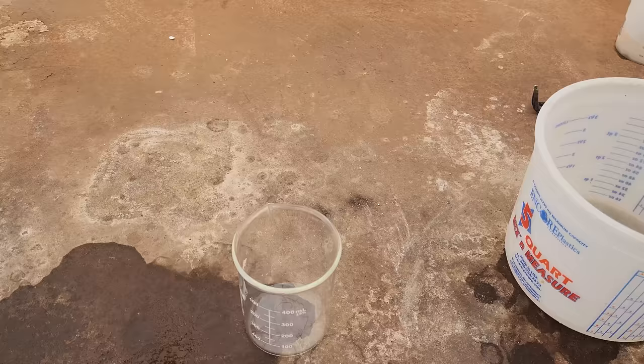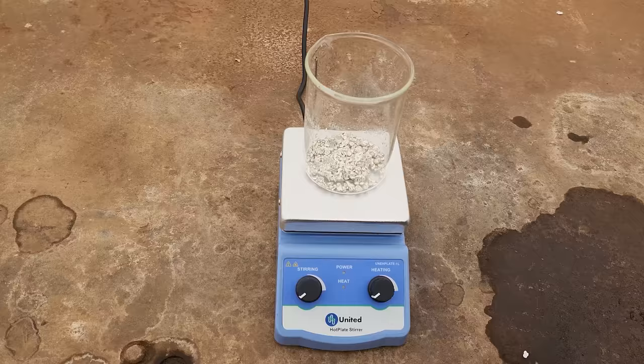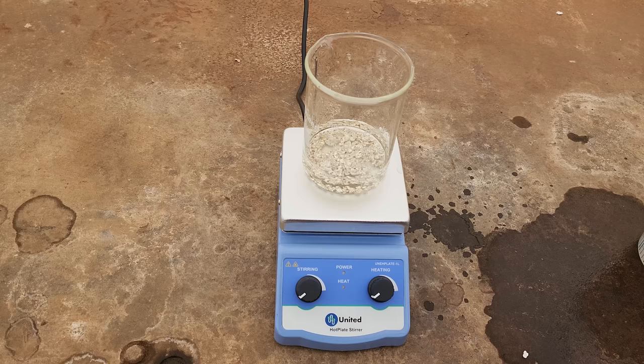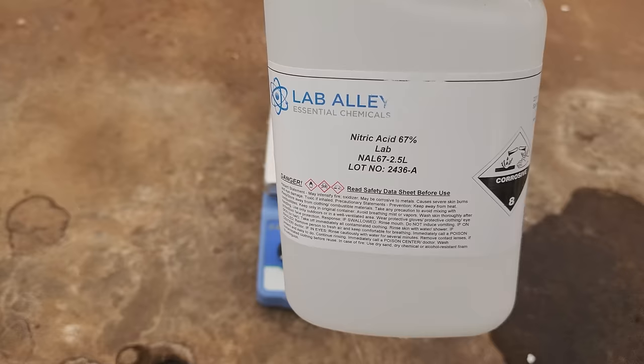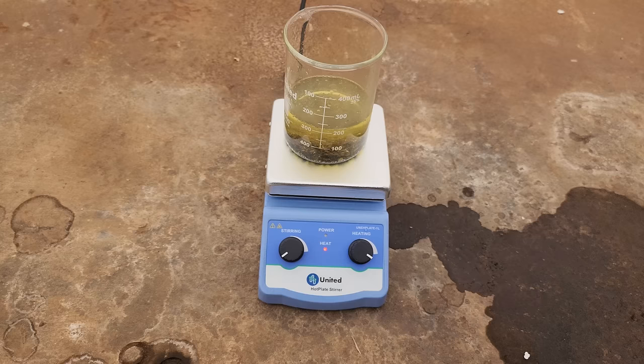Now I'm going to get all of our alloy moved over to this beaker here. I'm going to add about 100 milliliters of water. Then I'm going to add about 100 milliliters of nitric acid and turn the hot plate on and we'll get this boiling. But there's going to be some nasty fumes coming off of there, so I'm going to go put my respirator on. There's our nitric acid. I just added a little over 100 milliliters and it immediately turned brown. Now I'm going to cover